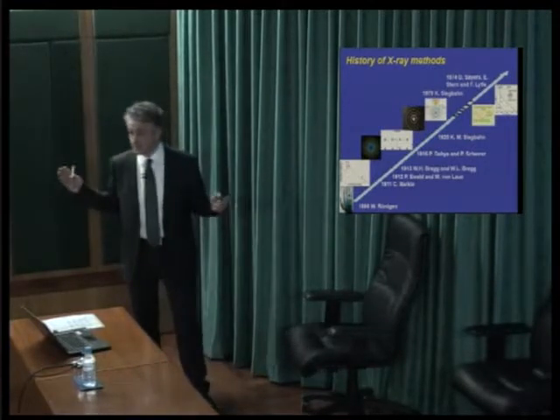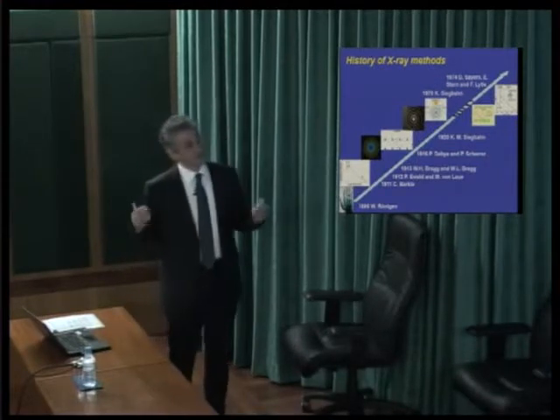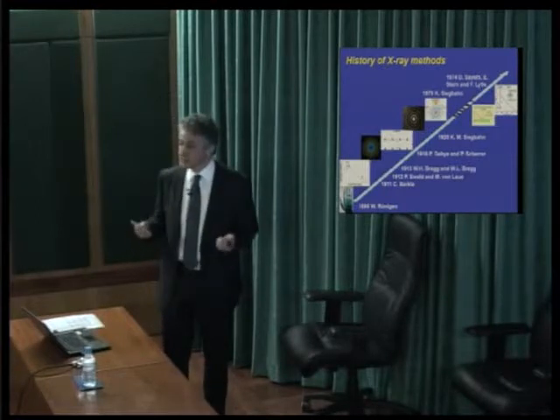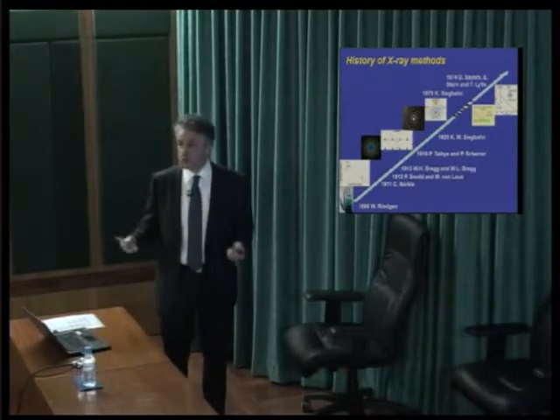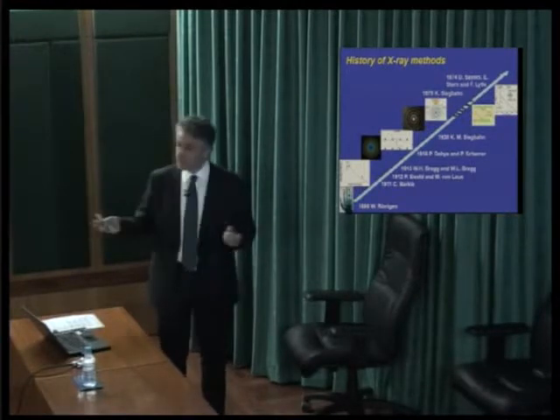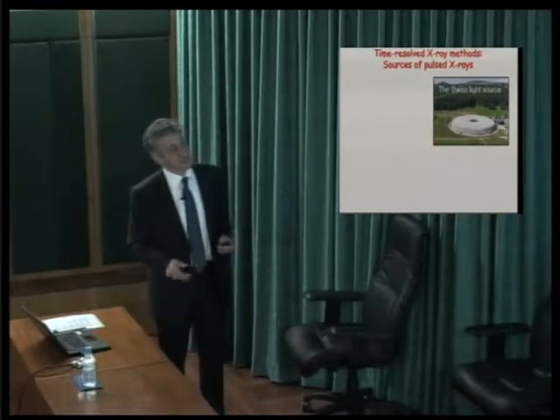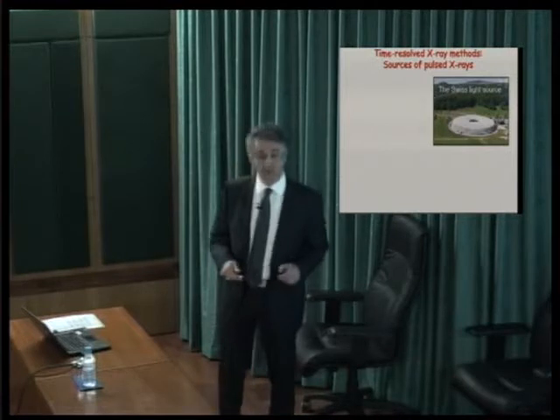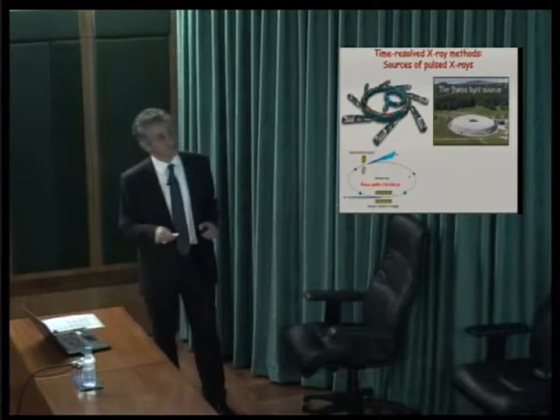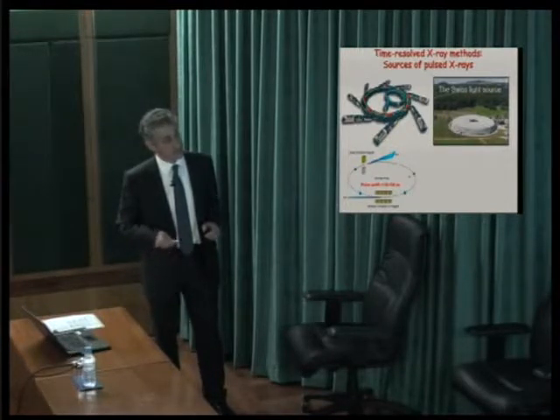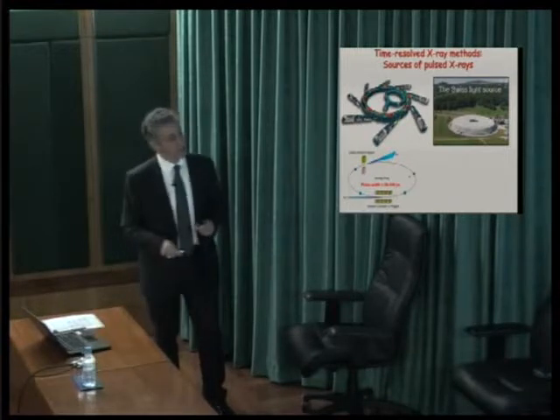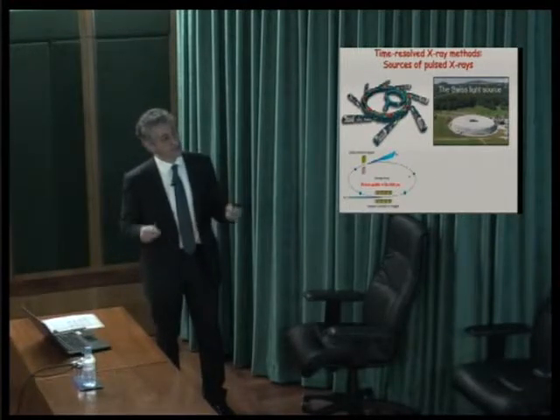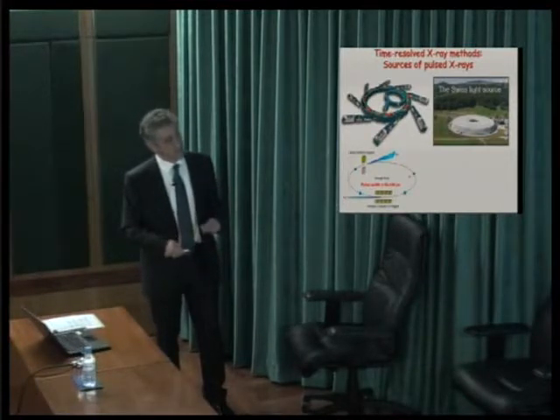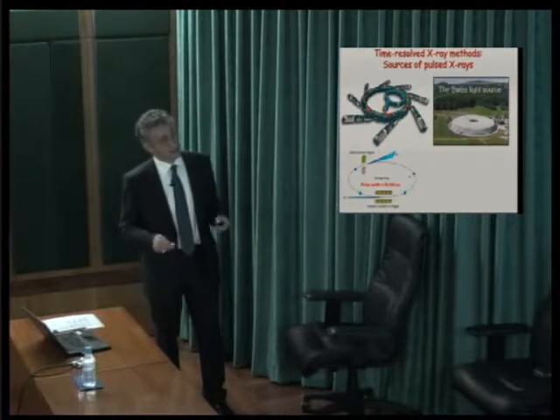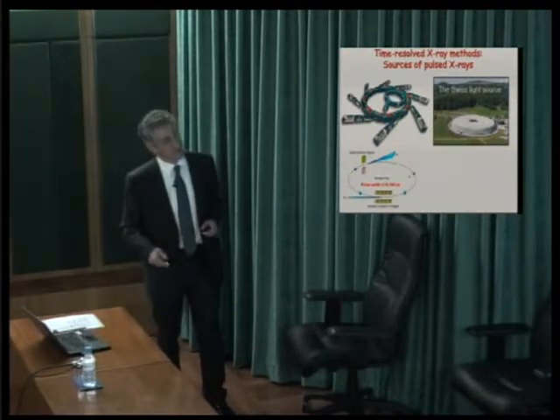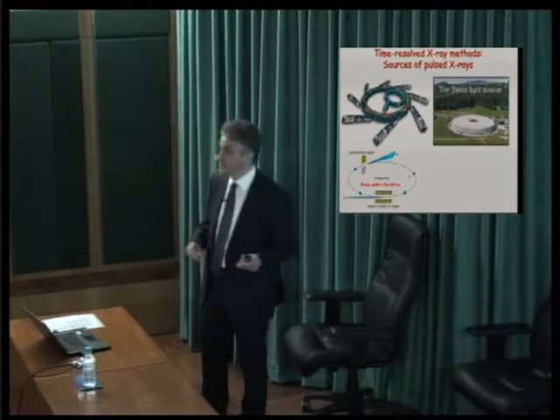Now, to do all these techniques with X-rays, and especially if you want to do them in the time-resolved domain, you have to have pulsed sources. When we started to develop time-resolved X-ray spectroscopy, there were no femtosecond X-ray sources, so we decided, okay, let's go wherever we can find them, and we had a synchrotron, the Swiss Light Source. Synchrotrons, as you know, are storage rings where you accelerate buckets of electrons at near the velocity of light, and every time they are deflected by a magnet, they emit electromagnetic radiation, which has some very interesting properties like tunability, a pulsed character, and a certain flux. Now, because of the physics of the storage ring, you cannot get pulses shorter than 50 to 100 picoseconds.